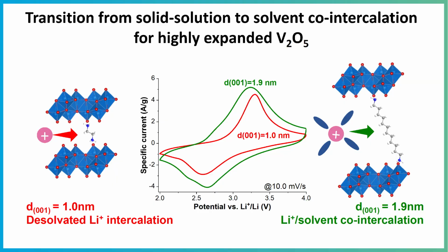Having established this, we went to the operando techniques, and this gave us the full picture. What it showed us was that in a small or medium interlayer spacing, lithium intercalates as a bare lithium ion. This is our classic solid solution intercalation. So you have your cell, and your lithium ions in your electrolyte along with your solvent molecules, and the lithium travels through your electrolyte. It goes to the interface between your electrode and your electrolyte, and the lithium ion strips off its solvent shell and then intercalates into your electrode material and takes part in the charge transfer process.